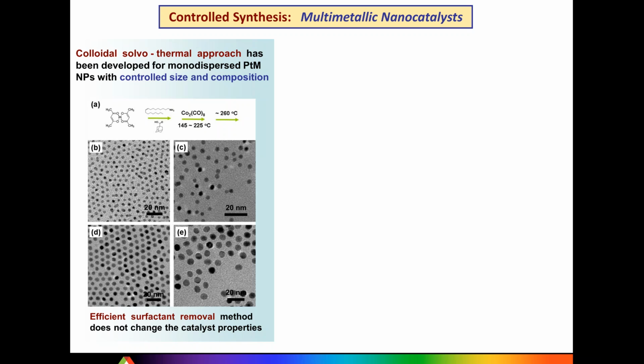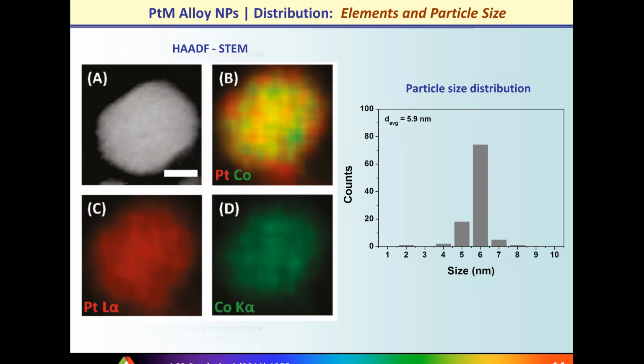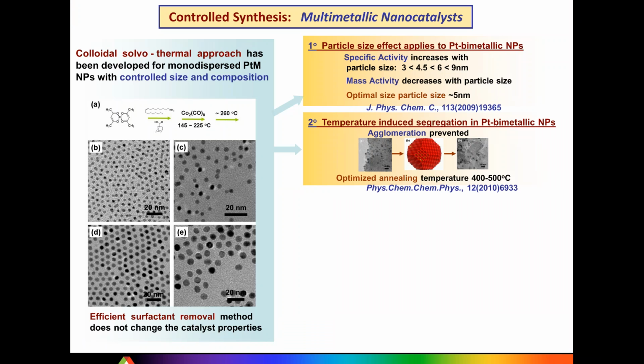So the first step is certainly to introduce size control, and the method of choice was the so-called colloidal solvo-thermal approach, which is a chemical method of making nanoparticles in such a way that we can be confident to claim they are coming as monodispersed, so a very narrow particle size distribution. So just to give you an idea how they look, those are not only pure metals, they can be alloys, and here is a representative example of platinum cobalt particles, which reflects extremely homogeneous distribution of alloying components along with a very narrow particle size distribution. So that was exactly what we were targeting. So at the same time, we were controlling both composition and size.